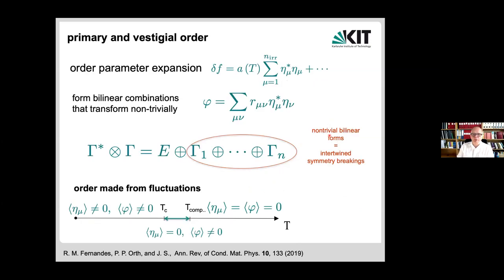To summarize, what happens is, as I said, you have a multi-component order parameter. You can build composites out of it. And if you want to know which symmetries you are really supposed to break here with composites, all you need to do, if it's a bilinear composite, is take the product of the representation and check which non-trivial representations occur. Those are the ones that you can still break at this upper transition and that could emerge. And those are the order parameters that can individually condense without the primary order parameter being finite.